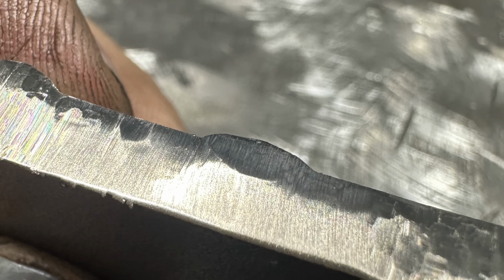Had I dropped the amperage to more or less get that bead to lay on the plate like caulk, it would have never cracked off, and you also get better wear resistance. Remember, because this is diluted with base material now, it's not as hard as it would have been if it was a bead of caulk. Oh well, let's move on.